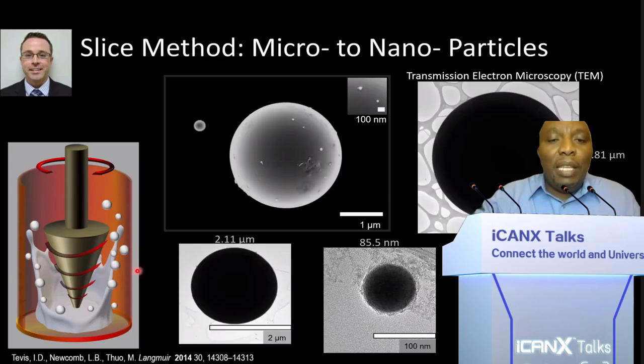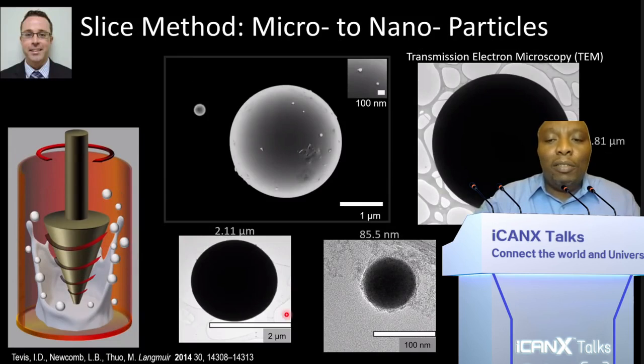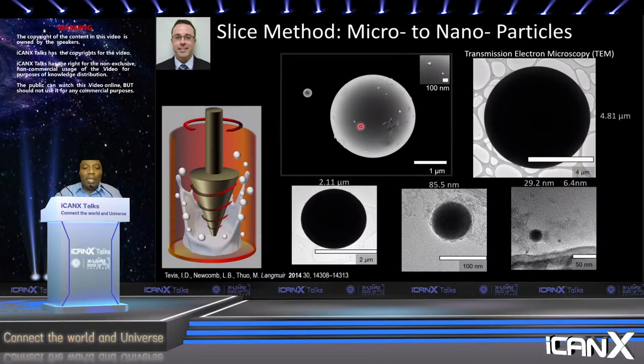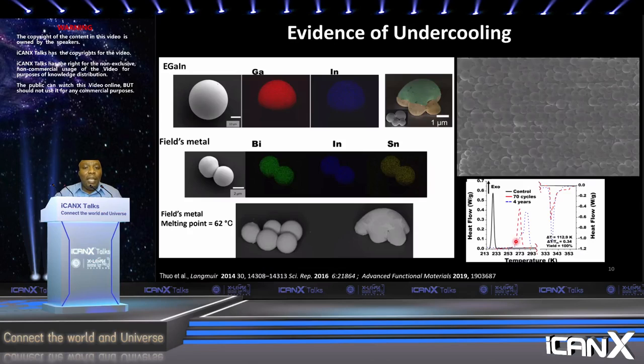And with this method, we can actually make particles of all sizes, from tens of microns all the way to nanometer scale. And first, we made particles from EGaIn, eutectic gallium indium. And as you can see here, these particles are fairly smooth. If you look at the distribution of the components, you see that gallium and indium are distributed evenly.